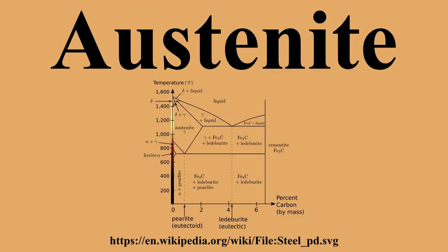Behavior in cast iron. Heating white hypereutectic cast iron above 727 degrees Celsius causes the formation of austenite in crystals of primary cementite. This austenitization of white iron occurs in primary cementite at the interface boundary with ferrite. When the grains of austenite form in cementite, they occur as lamellar clusters oriented along the cementite crystal layer surface. Austenite is formed by withdrawal of carbon atoms from cementite into ferrite.